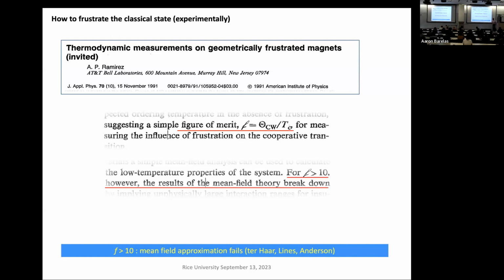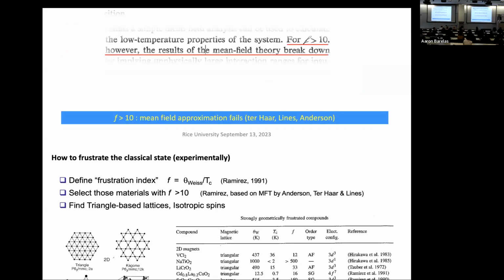Well, is it a class? Is it definable in terms of real materials? And I found that there were a bunch of materials that had, in terms of that 1/chi curve that I saw, a large ratio of Weiss temperature over Tc, where Tc is some arbitrary freezing temperature in spin glass. And for F greater than 10, there have been several papers by Ramirez and Anderson showing that mean field theory is about to break down. You need too many sublattices to describe any ordering process, but that's also a sign that the system is going to try to find other ways to get rid of its entropy and long-range ordering.